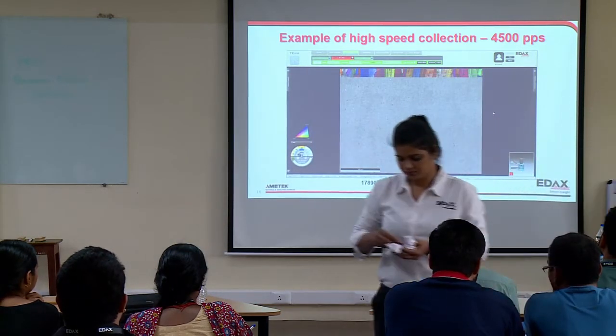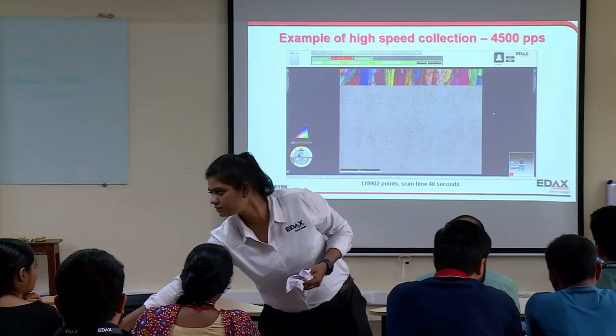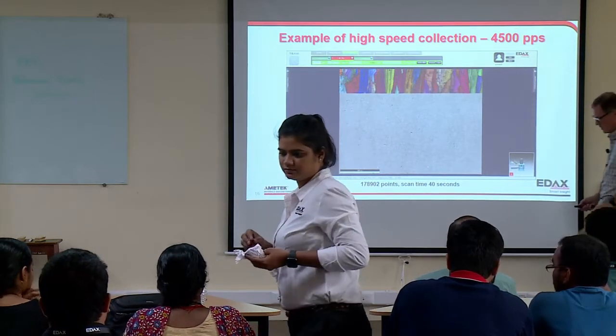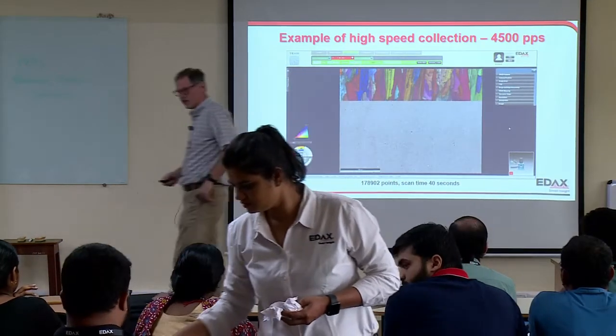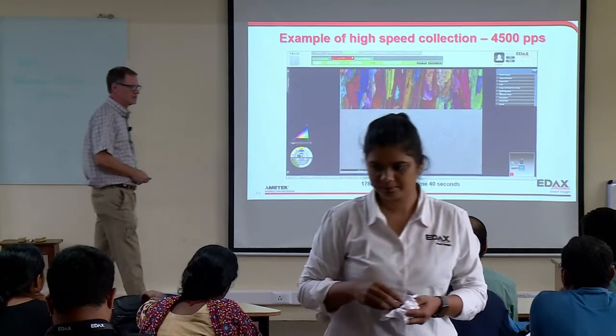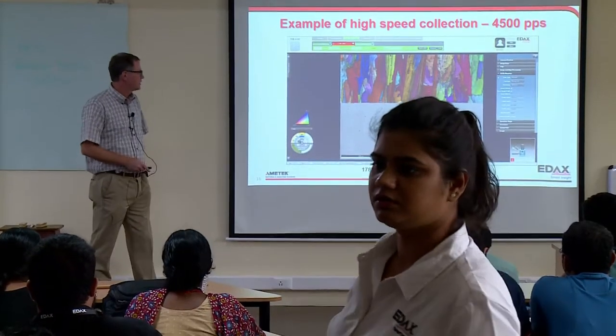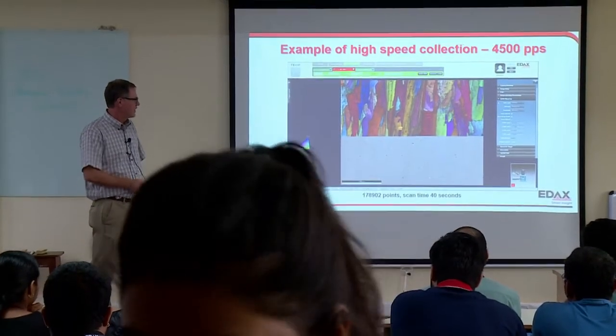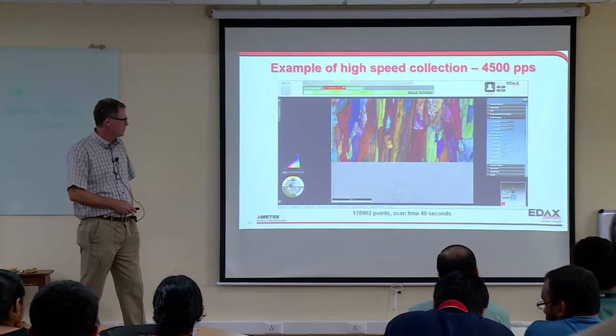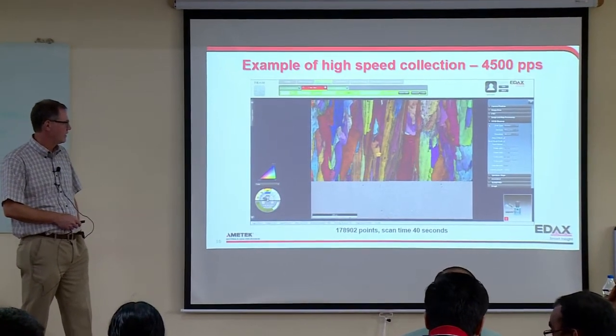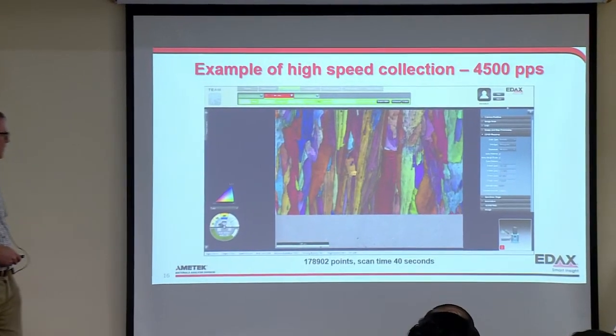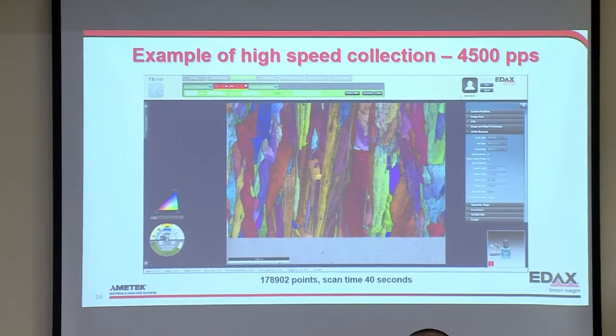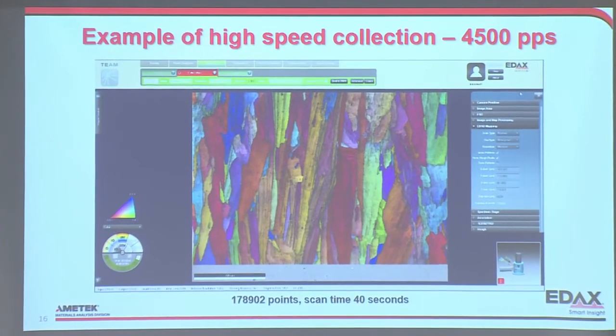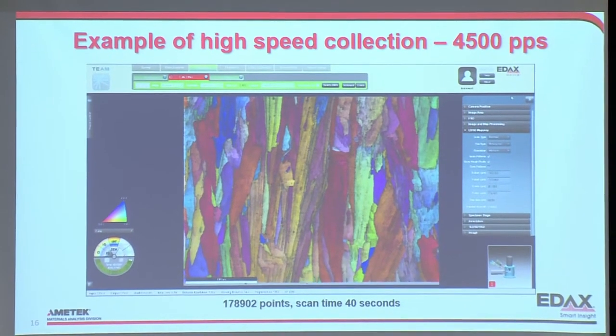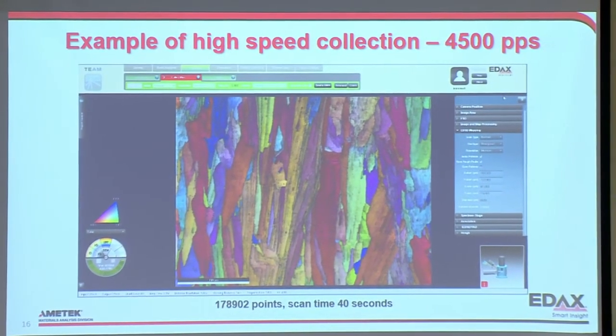So this is just to show you how fast this actually happens. I hope this works. You can see this scan is happening basically at slow scan SEM imaging rates. You're collecting all this data so quickly that you can get a scan like this that fast. You can see the indexing is very good. This is the orientation data in color, and then the grayscale behind that is the pattern quality. Like I said, that's pretty similar to running your SEM in a slow scan mode if you're looking for a really good image. So that took 40 seconds, and we collected 180,000 data points.